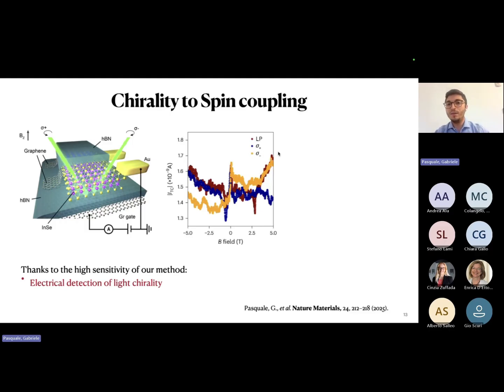So in other words, that means that with every parameter fixed, as we change the light chirality, we have a differential tunneling conductance that appears due to some intrinsic reasons in the material, which I don't have time to enter into the details, but it is linked to the fact that there is some spin polarization happening.